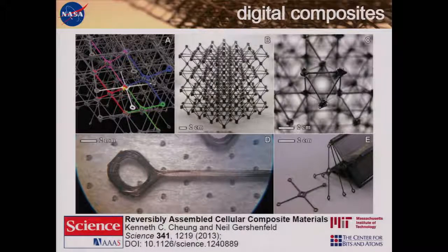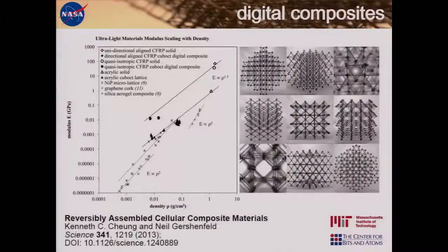And so at this sort of larger scale than amino acids, of course, recent work has shown that a building block approach can be used to achieve novel material properties in cellular materials with centimeter scale lattice pitch. So these are essentially three-dimensional optimized fiber composites. You get the unidirectional material performance scaling, but now in a quasi-isotropic cellular solid. So we've shown better specific modulus scaling than previously known ultralight materials, and this is possible because assembly allows us to produce geometries that have not been achieved with conventional ultralight processes.